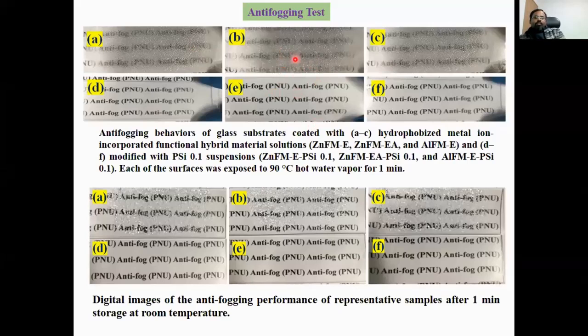When the water evaporates, the fog generated from the water is deposited on the substrate. On the hydrophobic coated substrate, more fog is deposited, which means, as I told, it can have more adhesion with water, so the transparency is also reduced. Whereas the super hydrophilic substrate stays completely transparent, because hydrophilic substrates can absorb water drops and water fog, and also let it penetrate into the surface interlayers, so that it can maintain good transparency.